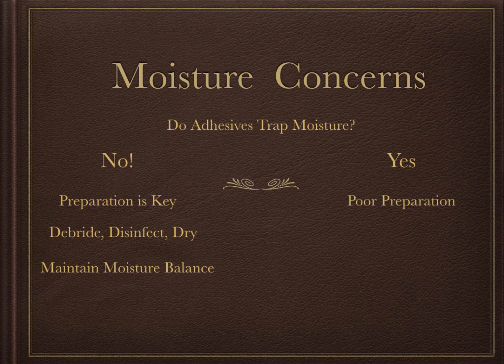Okay, so there are situations where adhesives do trap moisture, and mostly it's because of this. If you prepare an area poorly, the bond is not going to stay as well, and if a portion of the bond releases, now you've got a moisture trap. Now you've got stuff that can get underneath it and set up shop, and you certainly don't want that. So a lot of it is in the preparation, and also excess moisture. If you glue something on and then the horse goes out and stands in an irrigated pasture, well, that's kind of shooting yourself in the foot. It could be a waste of time and money.